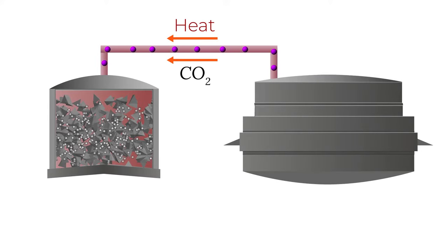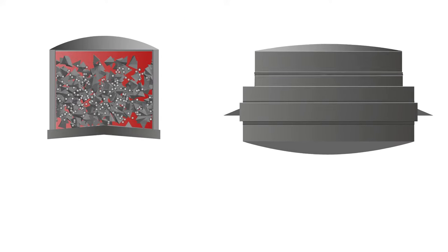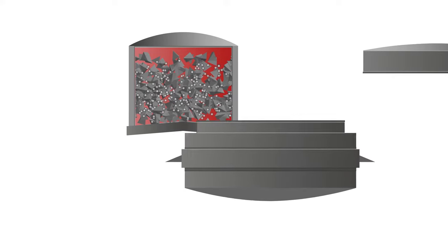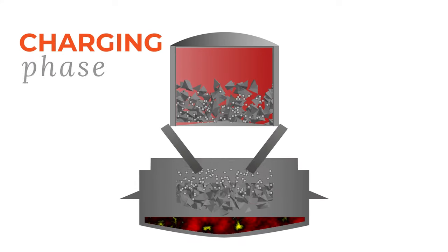The charge is usually preheated before adding to the electric arc furnace. Preheating is by hot flue gases from the previous cycle of electric arc steelmaking. The roof of the electric arc furnace is removed and the charge is added. This is called the charging phase.